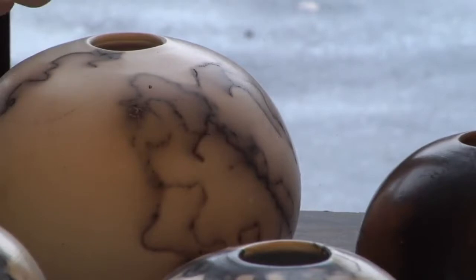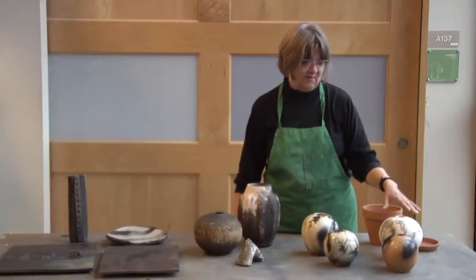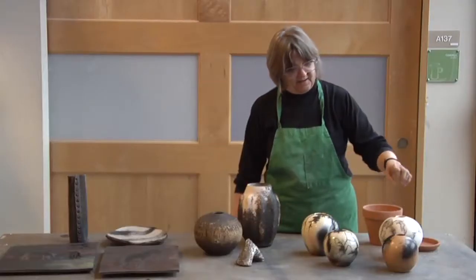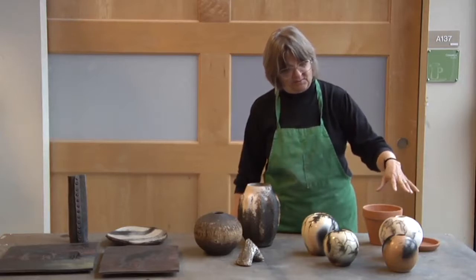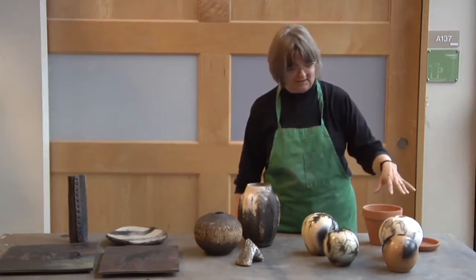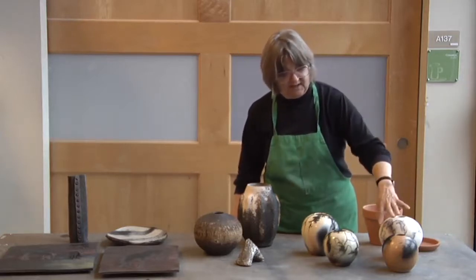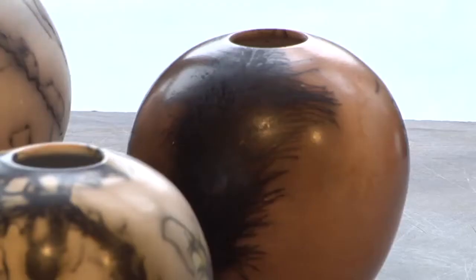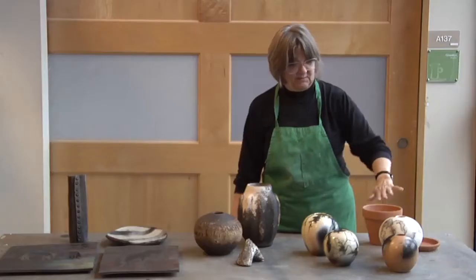And then this is fired in a raku kiln to 1150, taken out, and the horsehair and the feathers are applied to the surface and they're burned into the surface. If you get any kind of globs of ash or bubbly soot or whatever, you can clean it off with an oven cleaner, just with a sponge.